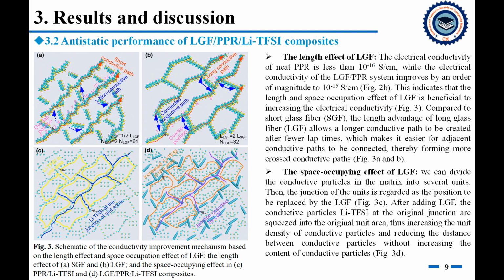Next, we give the schematic of the conductivity improvement mechanism based on the length effect and the space occupying effect of long glass fiber. First, the length effect of long glass fiber. Compared to short glass fiber, the length advantage of long glass fiber allows a longer conductive path to be created after fewer linkages, which makes it easier for adjacent conductive paths to be connected, thereby forming more crossed conductive paths.